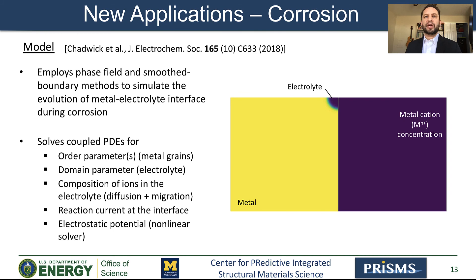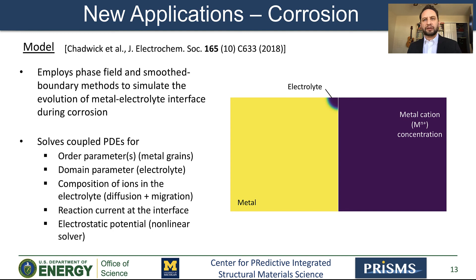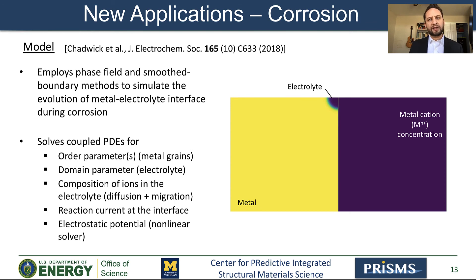Let's start with the corrosion application, which was released a few months ago. This application features the most complex model in a pre-built application to date. It uses phase field and the smooth boundary method to simulate the evolution of a metal-electrolyte interface during corrosion. The numerical solution requires solving coupled PDEs for the order parameter describing the metal, the domain parameter describing the electrolyte and marking the region where ionic transport is allowed, concentration of each ionic species in the electrolyte governed by diffusion and migration transport mechanisms, reaction current at the interface depending on the electrostatic potential, and finally the electrostatic potential for which we need the non-linear solver.